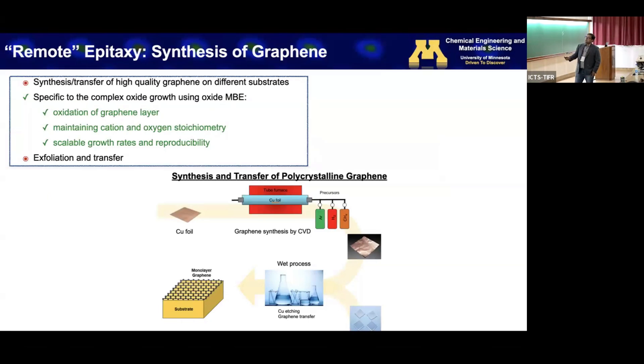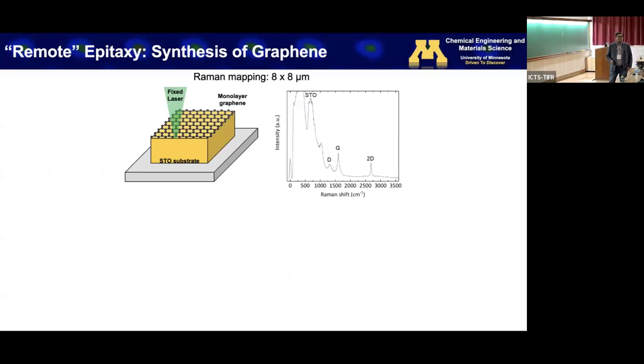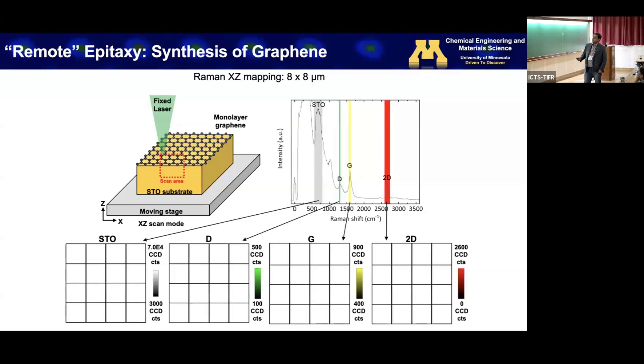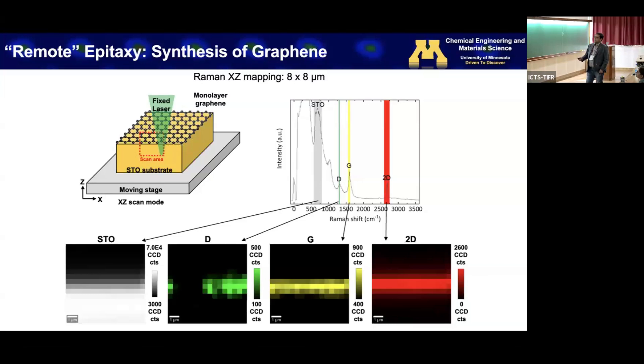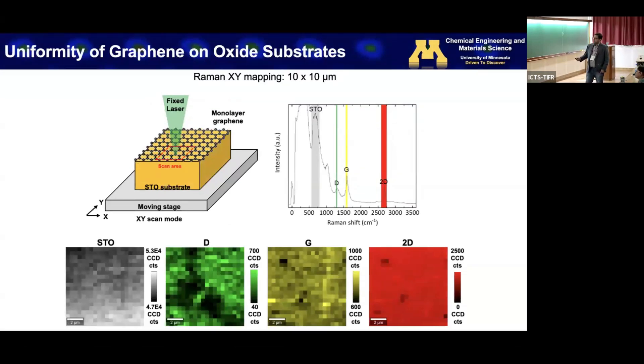We make our own graphene using a CVD process. We wet-transfer it — we use copper foil, dissolve the copper using HNO₃, and transfer the graphene onto a substrate. If we want bilayer graphene, we repeat the process. Once we have the graphene, we confirm its presence using Raman spectroscopy. We scan in X-Z direction to identify where graphene is, fix that position, then do an X-Y scan to check uniformity. We see a 2D peak, although there is also a defect peak, and graphene looks quite uniform.